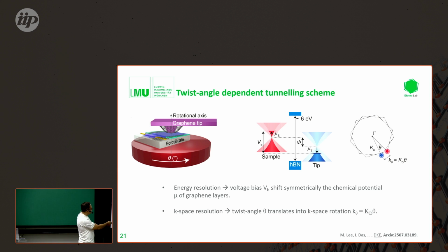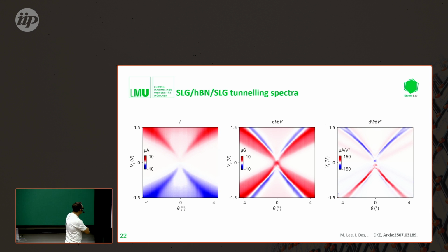And of course, if we rotate now, so if we look at graphene, it's just simple Fermi surfaces. If we rotate the sample, we're separating the distance in k-space between the two Fermi surfaces, so the twist angle separation results in a separation in momentum space, and for small angles this is basically equivalent to one another.